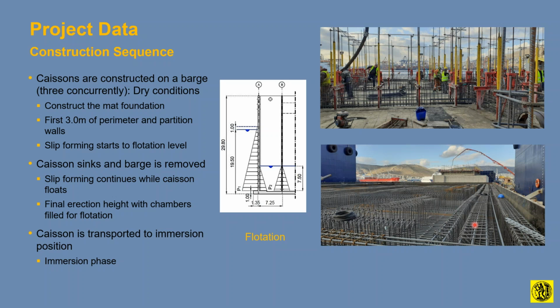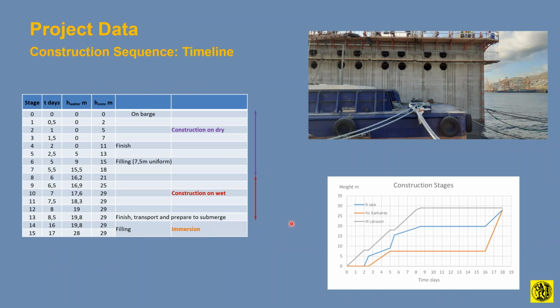And now these caissons are continued to be slip-formed near the port, and as they gain height, they continuously go deeper and deeper into the sea level. So this is the flotation condition, and at some point there is some ballast water added in order to provide stability for the final height of the caisson. So the flotation phase of the caisson is practically finishing on the fifth day, and already the caisson at that time is about 15 meters tall, and 9 meters of this caisson